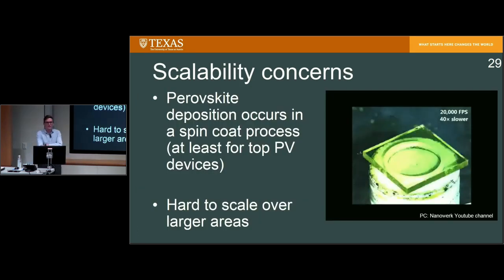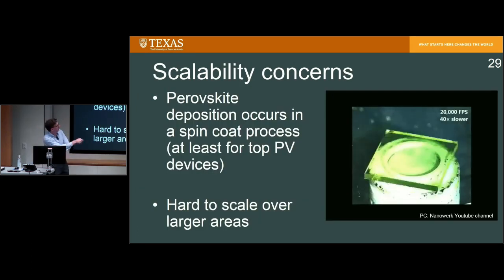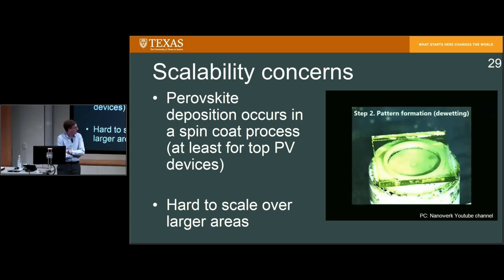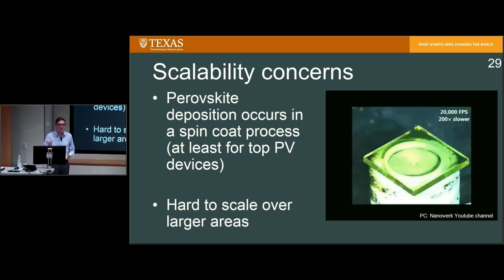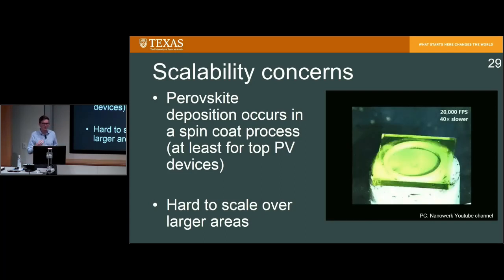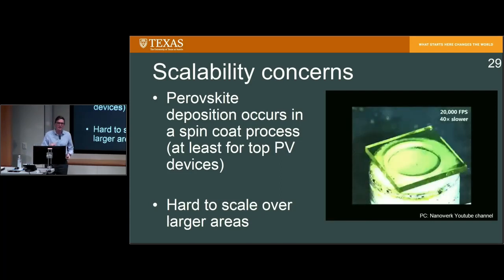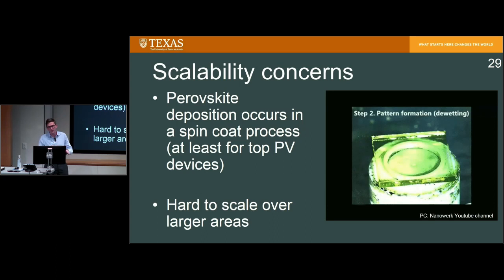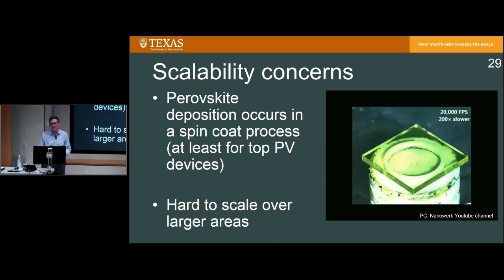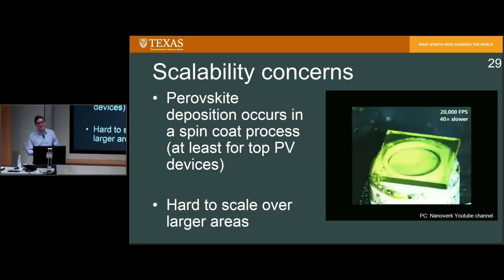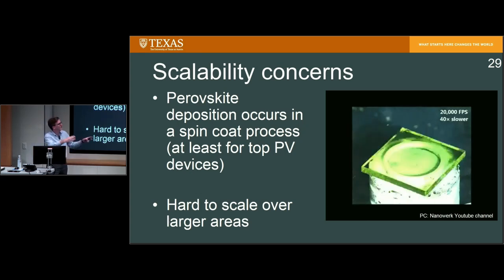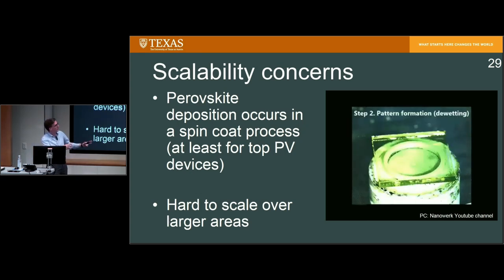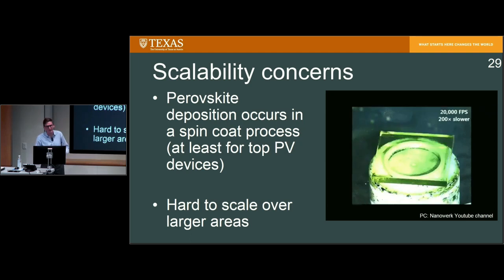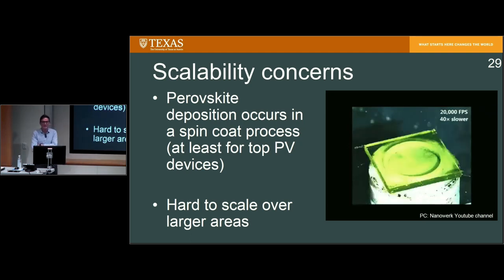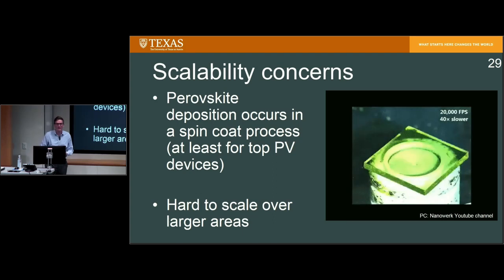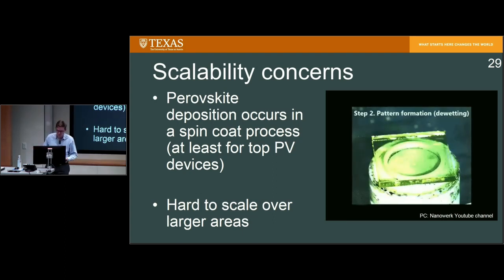The scalability concerns have also been an issue. So this is what a spin coating process looks like in general. Essentially what you do is you take your liquid precursor, your solution that you're going to process, and you spin it really fast. And this has the result of forming a very uniform, very thin film. And that's really great for making devices at a very small scale. But imagine taking a meter by meter squared square of anything and putting it through the similar process. It's not necessarily the best way to try to make very large area solar cells.